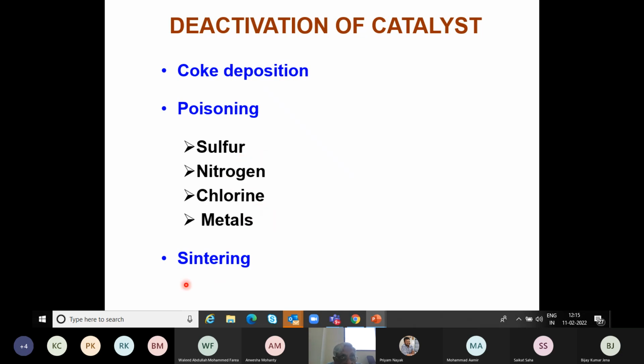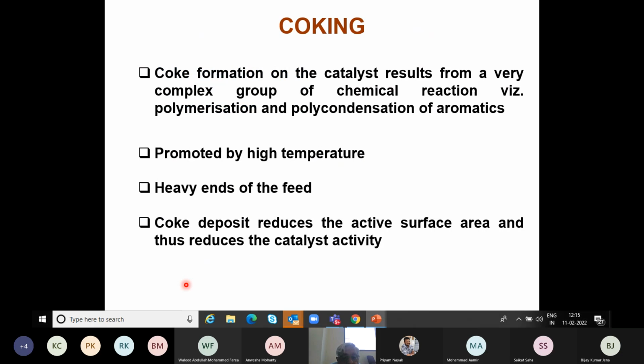And then over a period of time, because of the high temperatures that the catalyst sees, like 510, 520, 530 degrees Celsius, the crystalline structure of the gamma alumina gets shattered. So you get sintering or agglomeration, etc. This is a slow process. Of course, it takes roughly 4 to 5 years for this to start seeing some impact on the catalyst. Around 4 to 5 years, you are ready to change the catalyst.